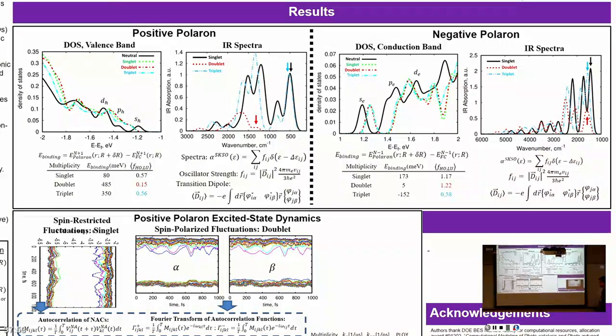I guess in an experiment, it's time resolved. So you have the ground state reference that has all the absorption, and if you assume the excited state doesn't have many additional vibrational peaks. Great. Another idea: if it is a femtosecond experiment, which is quicker than any period of nuclear vibrations, then there will be no chance for quantized nuclear degrees of freedom to appear there. If it's 10 femtoseconds or 50 femtoseconds, it will be all electronic transitions.